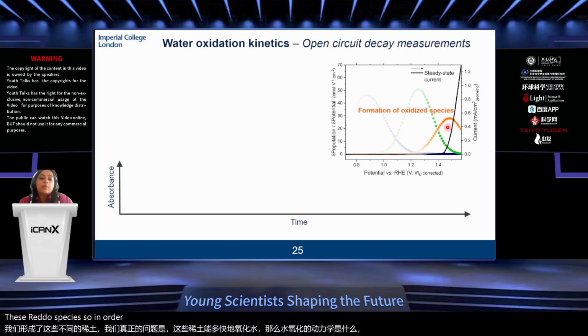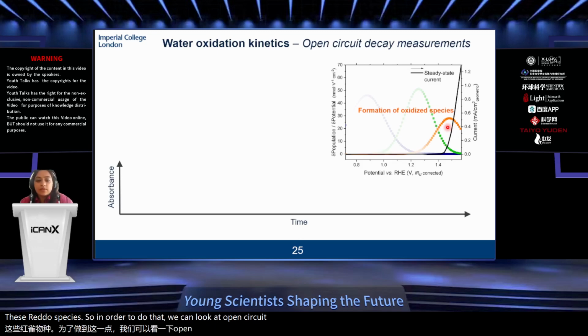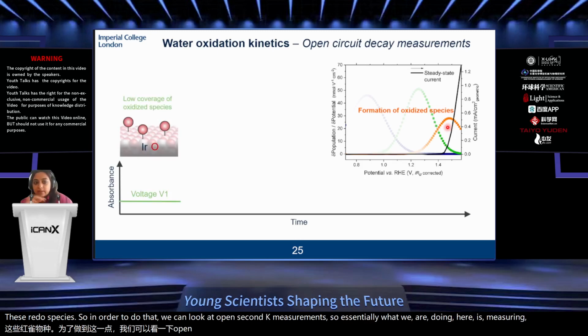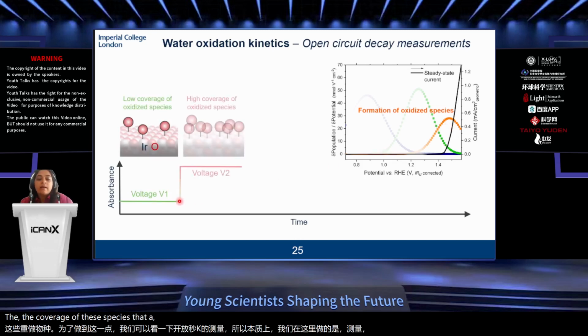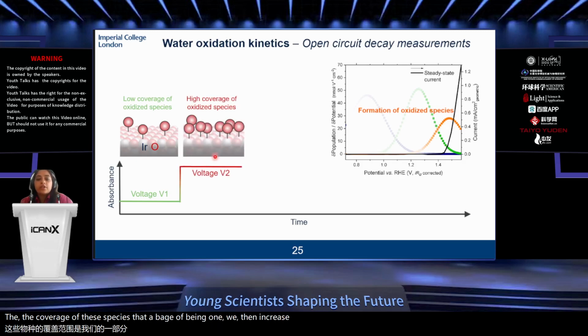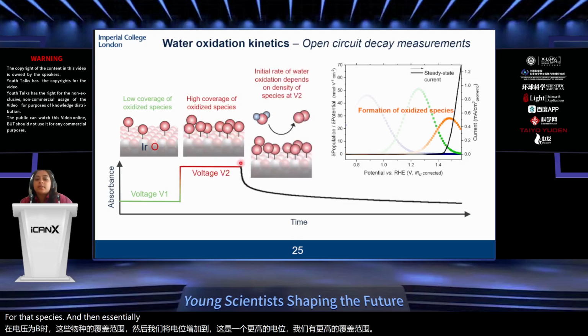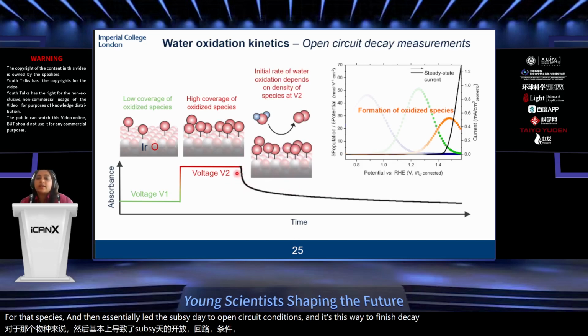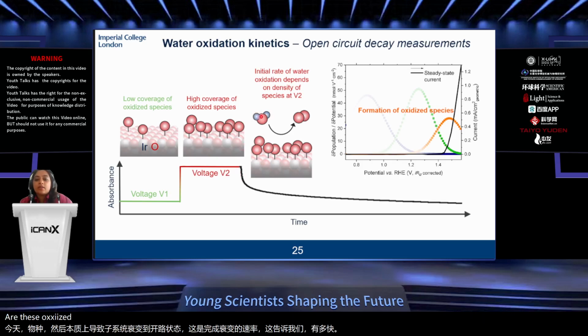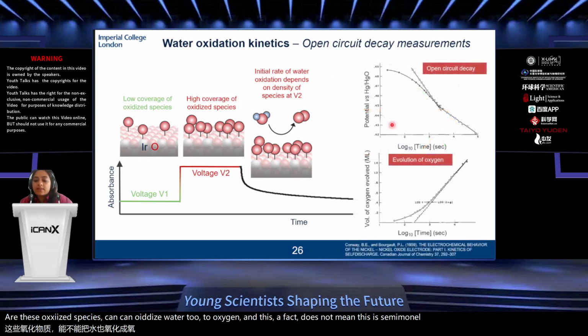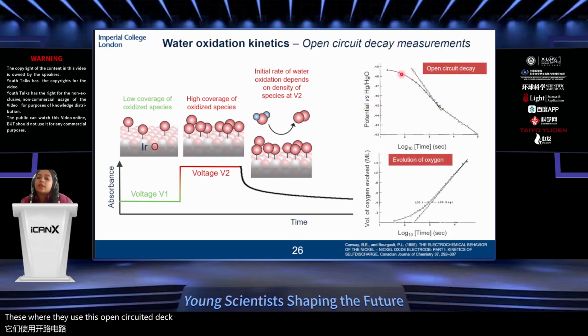In order to do that, we can look at open circuit decay measurements. So essentially what we are doing here is measuring the coverage of these species at a voltage of V1. We then increase the potential to V2, which is a higher potential where we have a higher coverage of these oxidized species, and then essentially let the system decay to open circuit conditions. And it's this rate of initial decay which tells us how quickly these oxidized species can oxidize water to oxygen. And this, in fact, is not new. This is seminal work, for example, by Conway in the 1950s, where they used this open circuit decay concept to measure the first Tafel slopes on nickel-based oxides.